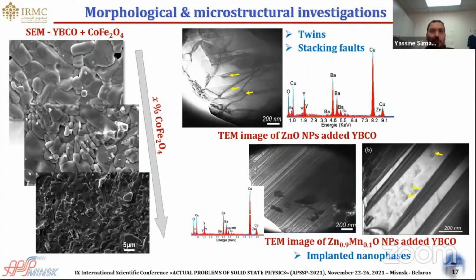Here there are also some examples of TEM images of other kinds of magnetic nanoparticles added to YBCO superconductors, which reveal the presence of relative contrast and high density of twins, stacking faults, as well as the formation of nanophases within the prepared YBCO compound.